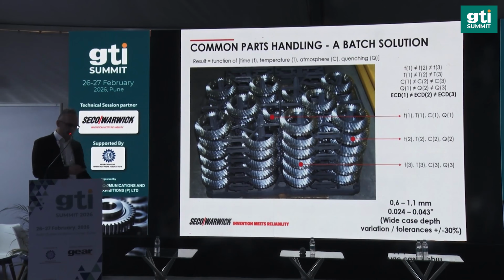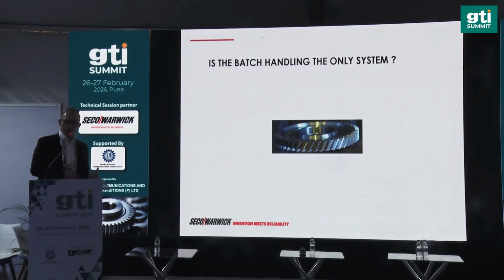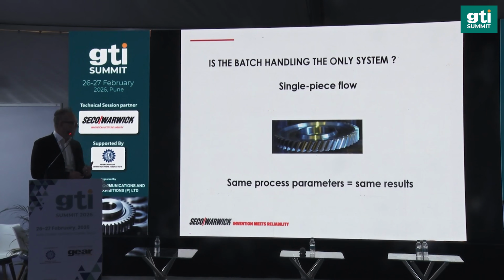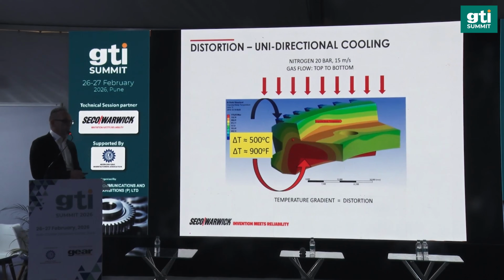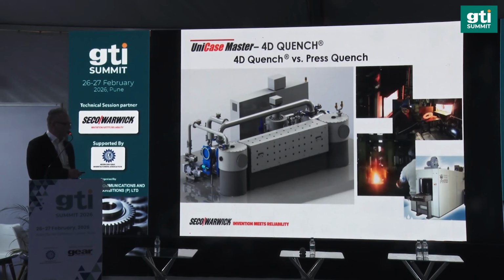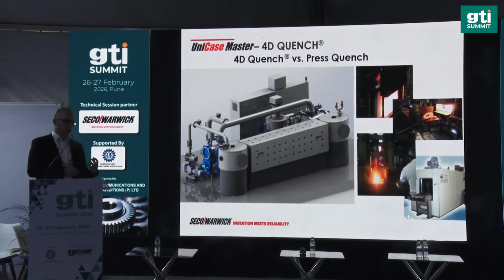However, all those examples were correlated to batch type heat treatment, but we also have a solution where, instead of batch type approach, we have a single piece approach, giving you much more benefits, especially in consistency in the shape of the parts after heat treatment, due to the different heat gradient through the hardening process at several points of the parts, especially when you treat the whole batch of the parts. Therefore, we have got a solution where we treat each part individually, providing the consistency of each part being treated the same way, giving you the same results in terms of quality and distortion level, and at some point being an alternative to the typical press fixture quenching.